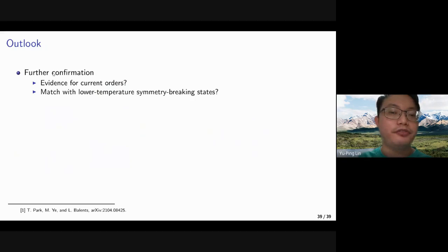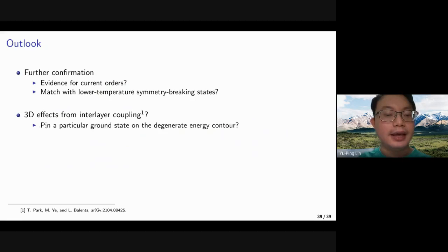First, we may try to further confirm the evidence for the current orders, for example, in the experiments. And we may try to match it with lower temperature symmetry breaking. And it has also been proposed in the recent theory work that the 3D effects might be relevant from the interlayer coupling. That is, we may be able to couple the CDW orders between different vanadium layers. And our interpretation is that it might be able to pin a particular ground state in the degenerate energy contour as we saw from the free energy minimization.